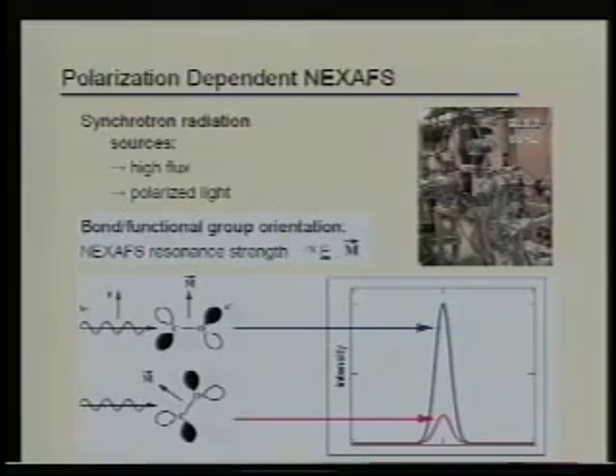the text, they call this plane molecules. And there's three slides at the end of the talk where this describes it in complete detail, which I didn't put in the presentation per se. But what happens is if in a plane molecule where you have pi bonding, if the electric field and the transition dipole matrix align, you get a maximum in the blue curve. If they're orthogonal to one another, you get a minimum. Now that's different if you have sigmas, it's opposite.